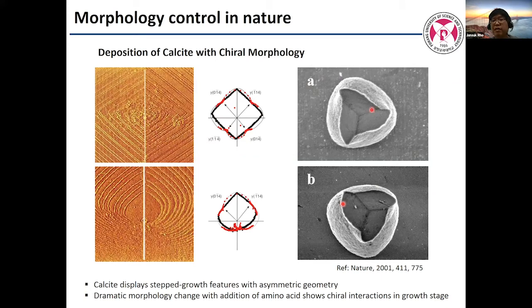We have some clue. So this is a shell. This is a biology paper. They show the shell growth mechanism. So we know the shell eventually has a helix, but when it is born and grows up, it doesn't have a helical structure at the beginning. Its growing speed is the same everywhere. So no chirality here, but at a certain time, this helix starts to be made. And the biologists found that a certain protein level dramatically increased when this happens. So this chirality is related to this protein somehow, is our hypothesis.